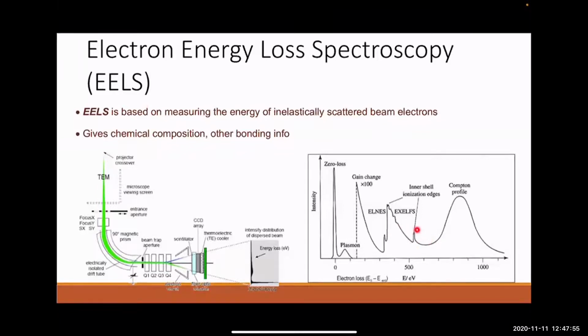And while it can give you similar information to EDS, it can give you much more information as well. There's very complicated EELS, extended energy loss, and near-edge structure. It's kind of complicated, but it can give you more information on things like oxidation states, Fermi densities, things like that. So it's quite a powerful technique in its own right. And you can do that on a TEM that's equipped with an EELS spectrometer. An EELS spectrometer is basically a way to take the electrons and disperse them according to their energy so you can get the spectrum. So very useful technique.